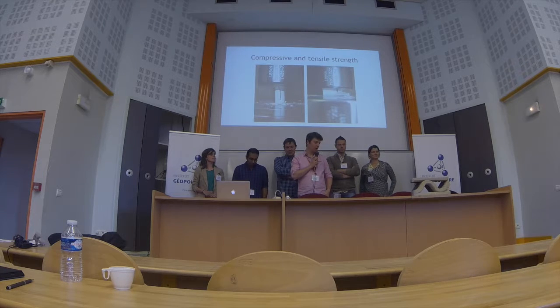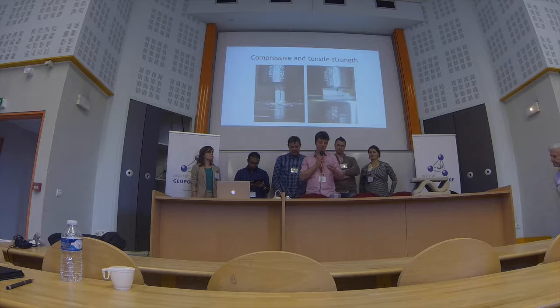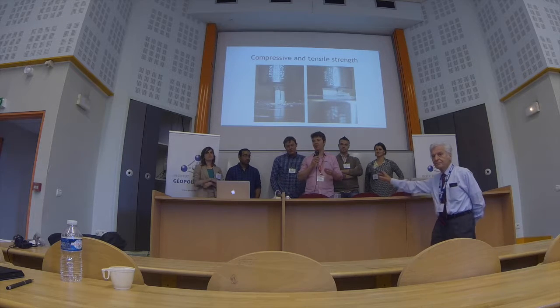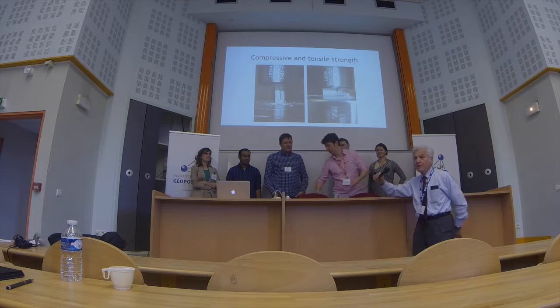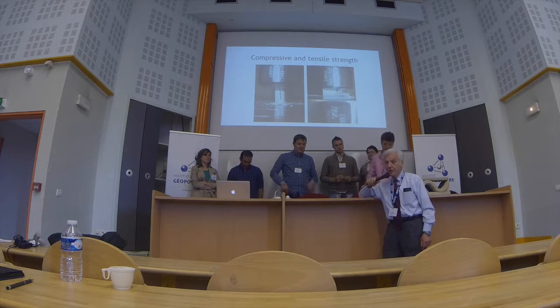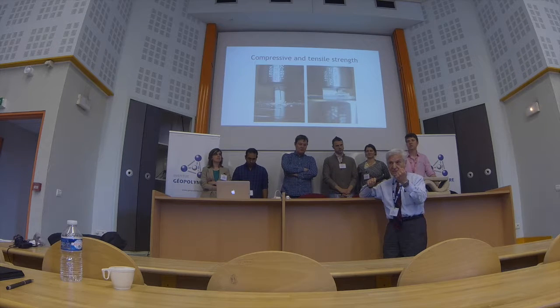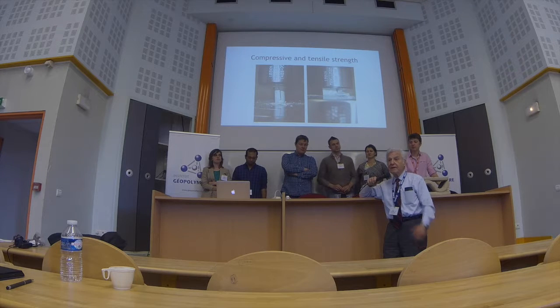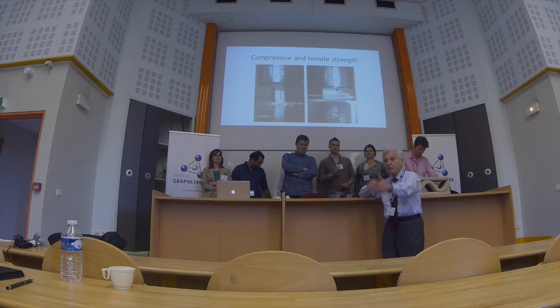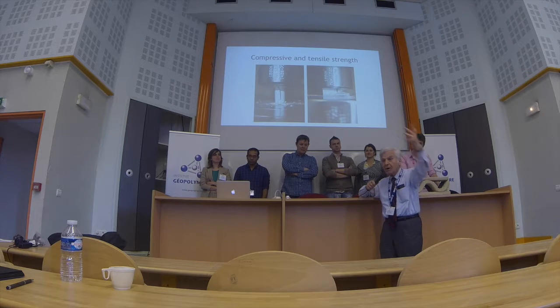And it's not comparable because the way to manufacture a ceramic with very high temperature requires a very different process. Okay, fine. So he's not aware of the geopolymer technology. Ceramic has to be fired at 1200 or 1400, depending on what you are asking for, before you get the strength, whereas here it is at 60, 80 degrees C. Ceramic can be used up to 1200 and so on, or at 200. Even ceramic used at room temperature, like your dishes or your fridge, has to be fired. Otherwise, it has no resistance.